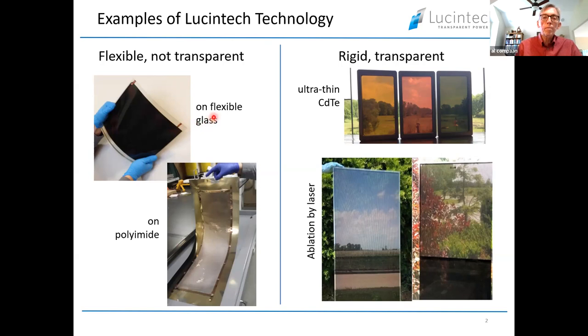But for a variety of reasons, we felt that the flexible product line was not going to be our best approach to commercialization. So we transitioned to going to a semi-transparent product. And so after a few years, we worked on developing ultra-thin cadmium telluride. And this is a small prototype, only 3 inch by 5 inch. And this is a typical color of cadmium telluride when you have only about a third of a micron of cadmium telluride. We developed a process to change the colors,